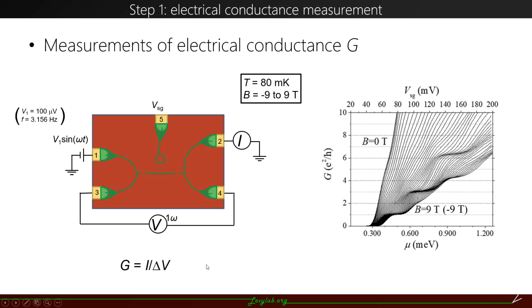We measure the electrical conductance as a function of side gate voltage, which is linearly proportional to the chemical potential, mu, at a low temperature of 80 millikelvin in different magnetic fields from -9 to 9 Tesla. So this is one of the typical results. We can see that the conductance increases with chemical potential and decreases with magnetic fields. So in some high magnetic fields, for example 9 Tesla, we see that the electrical conductance increases with steps, which shows the quantized conductance.